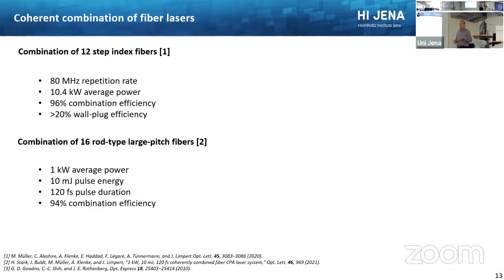We built a system based on flexible step index fibers. This is really optimized for the highest average power with 12 channels, and we achieved over 10 kilowatts of average power, also with a very high combination efficiency of these different channels. At this point, your overall wall plug efficiency, so the electrical power you need to operate this, becomes quite important, and we achieved over 20% for the whole system. Now, if we start from large pitch fibers with larger core diameters, we can also have a system with 16 channels running at a kilowatt, 10 millijoules of pulse energy, 120 femtosecond pulses, also with high combination efficiency. This is also a system we use every day in our lab.